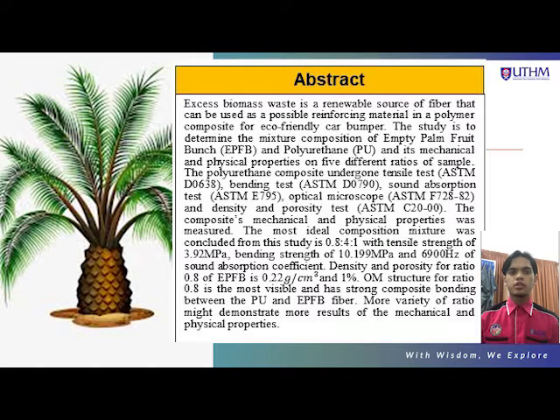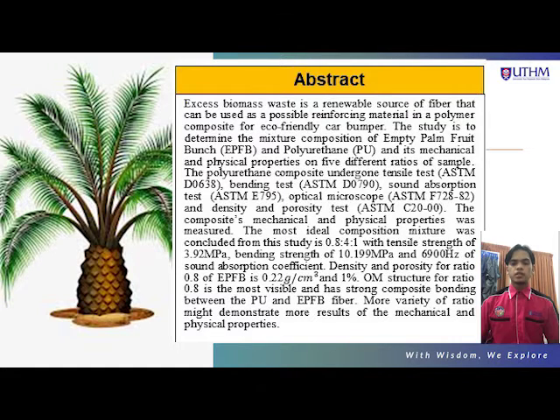For its physical properties, the density for the ratio 0.8 of EPFB is 0.22 gram per centimeter cube and only obtain 1% of porosity. For the optical microscopy test, the structure for ratio 0.8 of EPFB is the most visible and has strong composite bonding between the PU and EPFB fiber. For recommendations, more variety of ratio might demonstrate more result of the mechanical and physical properties for the samples.